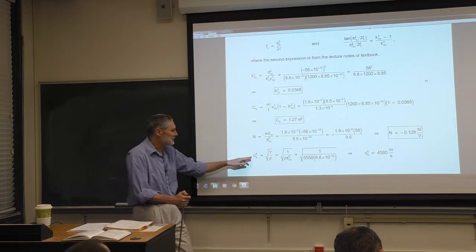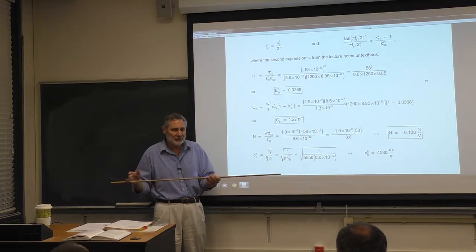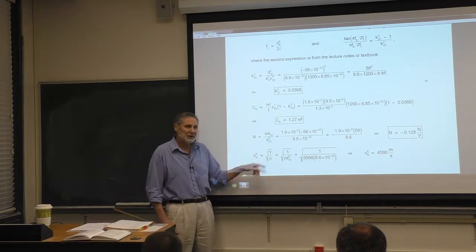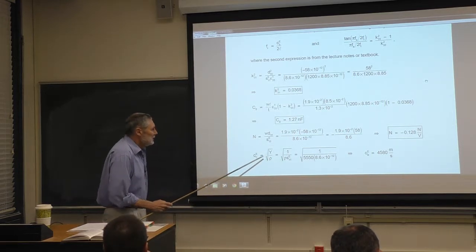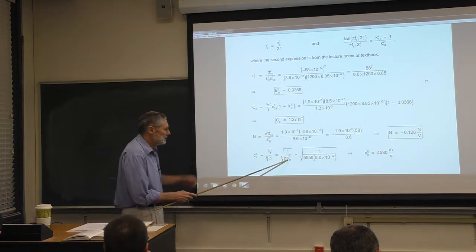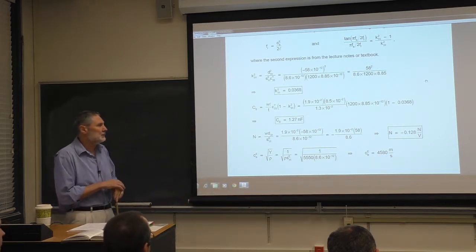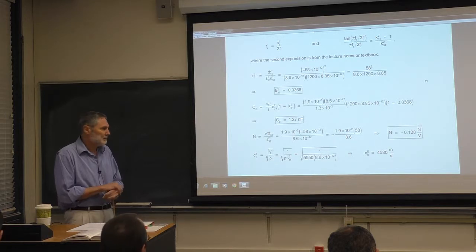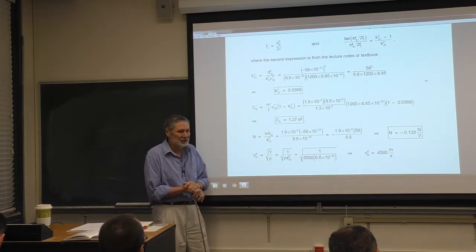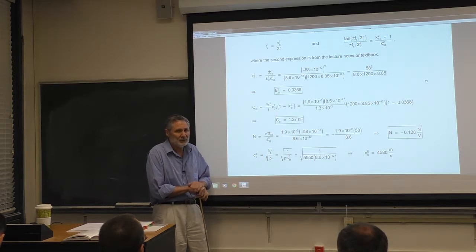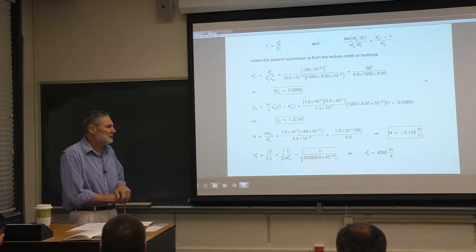Resonance frequency. We need to know the speed. This is the speed of sound for waves here. These are compressional waves where the wavelength is assumed to be long compared to the transverse dimensions. So Young's modulus is operating. You've got bulging and contraction here because it's long wavelength compared to the cross dimensions. So the Young's modulus is 1 over the compliance, as we've seen many times. Plug it in, get an answer, and it's typically kilometers per second, right? So if you get a speed of sound of hundreds of meters per second in a solid, especially piezo ceramics, you made a mistake. That happened to one group, right? So you want to notice these things. This is typical for sound in almost all solids, thousands of meters per second.